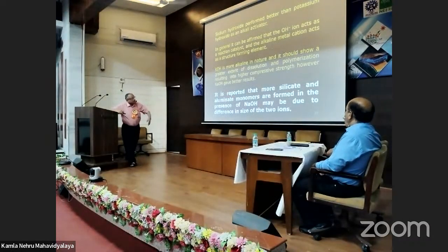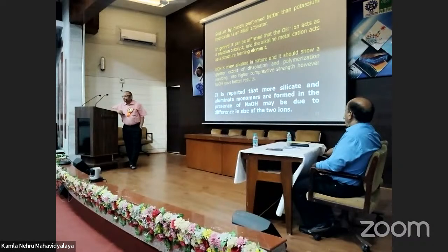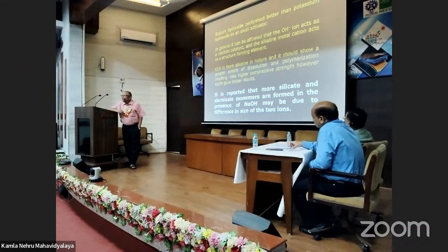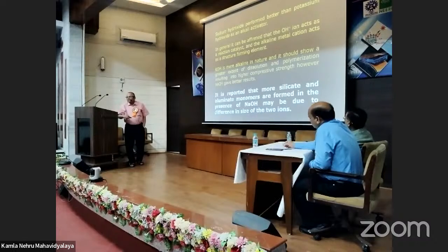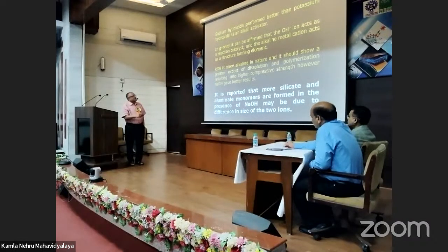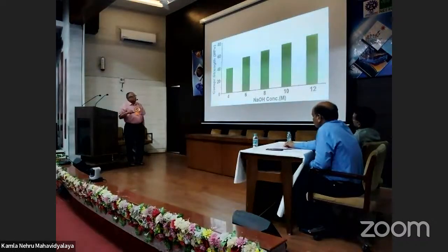it is reported that more silicate and aluminate monomers are formed in the presence of sodium hydroxide, maybe due to the different size of the ion. Of course, a different answer or different solution to this problem is not known. We can only guess that this may be the reason why sodium hydroxide acts in a better way.